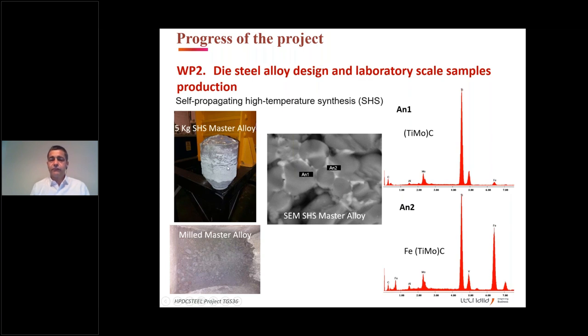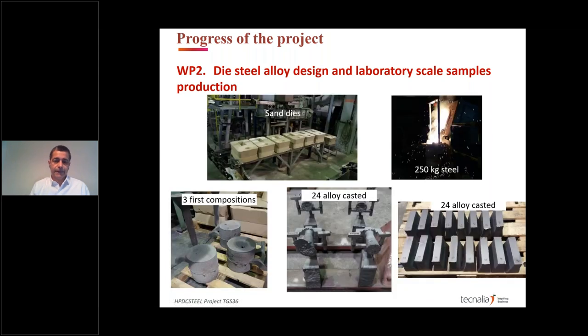This is a master alloy that was made at atmospheric conditions, not in a reactor. And we also were capable of working with ferroalloys instead of working with pure materials such as titanium or chromium, or molybdenum, excuse me. So here we can see, for example, this area, the white area, is the iron area, and this other is where there are the carbides. Here we see the master alloy milled, and here how we have obtained the 5 kilogram master alloy.